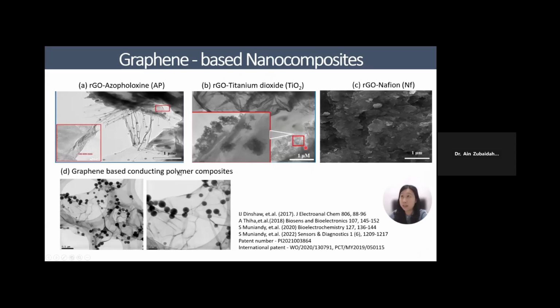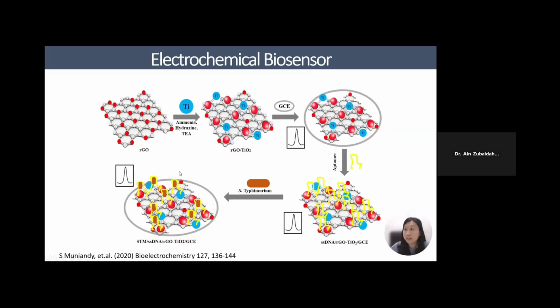In our research team, we develop different kinds of graphene-based nanocomposites. Can be RGO AP dye, RGO titanium nanoparticles, RGO Nafion, and graphene-based conducting polymer composite. As we know, GO, even though it's hydrophilic, tends to aggregate due to the van der Waals force and pi-pi stacking interaction between the adjacent sheets. So if we use GO, it's very difficult to disperse in solutions. If we make it into a nanocomposite, first it can enhance the sensitivity, and second it can help the GO to disperse well in water. So these are the developments.